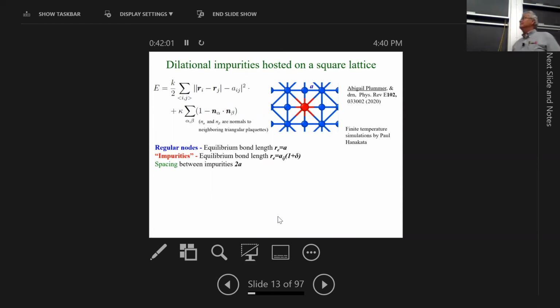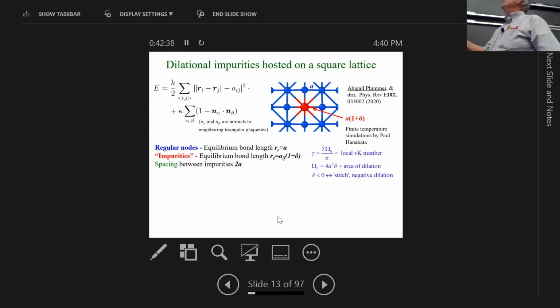So we made a simple lattice model with springs and so forth, and we put in large atoms. Say every other site will be a large atom with a longer rest length in the plane, but we allow it to buckle out of the plane, and we allow it to have free boundary conditions on the edge. Maybe it's periodic boundary conditions, but it can adjust its area. And so what Abby did was to study this thing, and you basically take this particular particle and you force its rest length to be a little bit bigger.